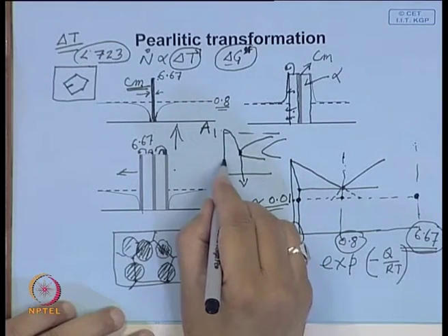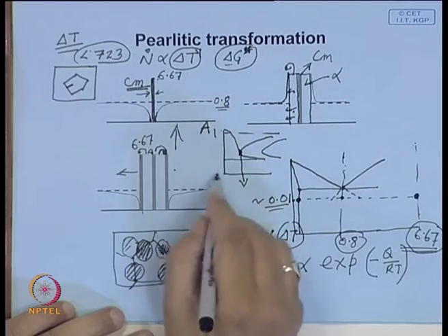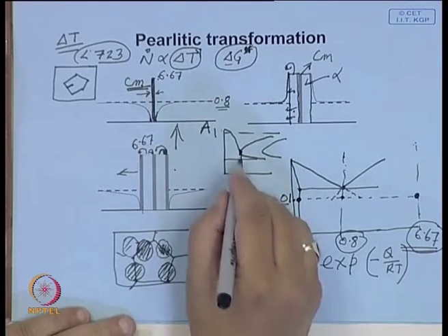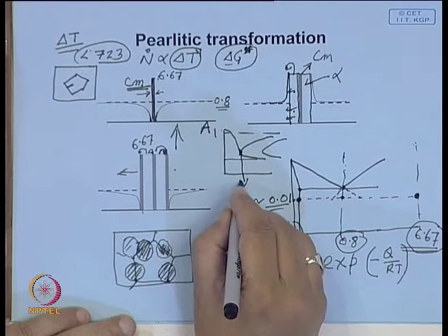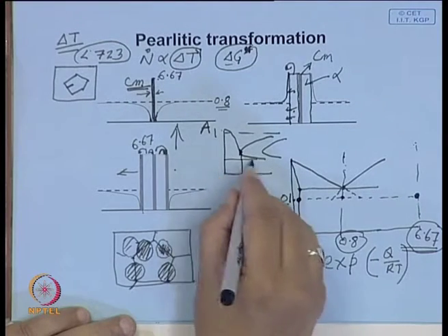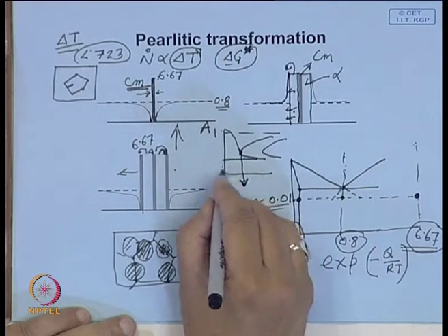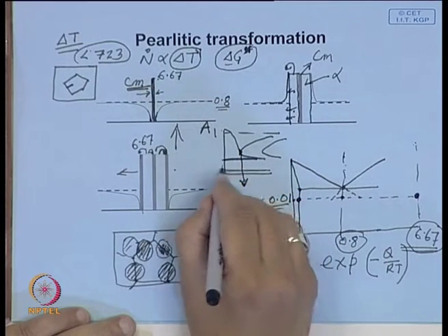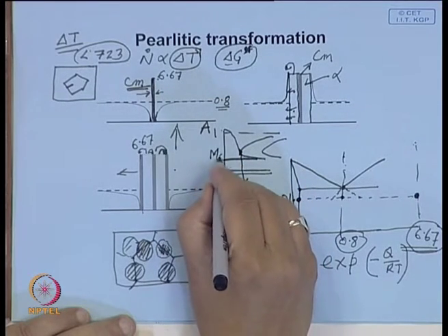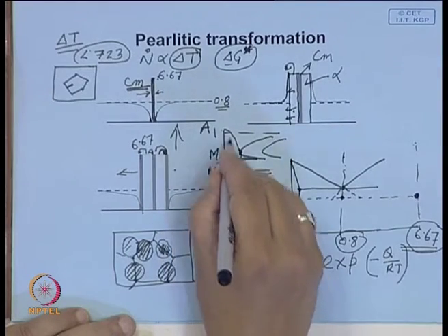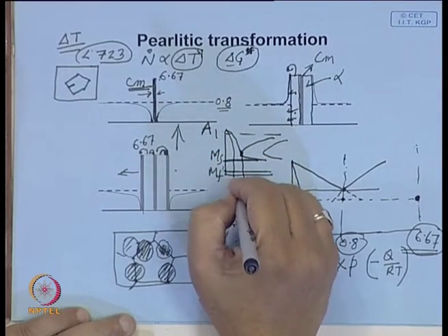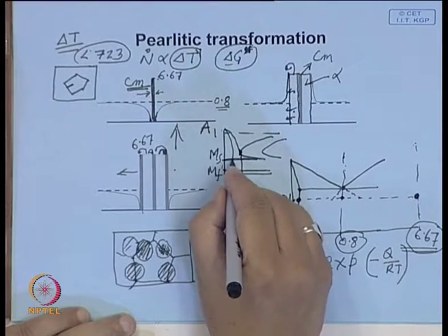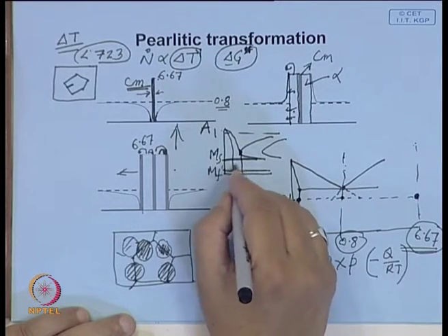austenite into pearlite through a diffusion controlled transformation. But if it exceeds that, martensite is something where we do not allow the diffusion to take place. So, that is why it is so fast, there is no C curve, you do not see anything, it is just parallel lines. This is the martensite start temperature, this is the martensite finish temperature, and as we go on we will look at the kinetics of martensitic transformation.